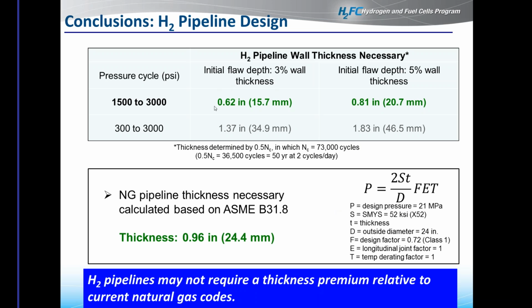And so what this really means is that using experimental work and a fracture mechanics-based approach, we see that for hydrogen pipelines the actual thicknesses that we need aren't any thicker than the current natural gas. Now, we wouldn't prescribe that the pipe should be thinner than natural gas, but nonetheless, what it basically says is that we don't need a thickness premium on these hydrogen gas lines as opposed to natural gas, based on the current natural gas code.